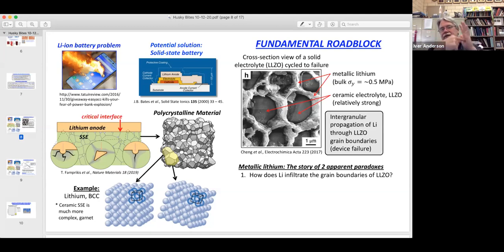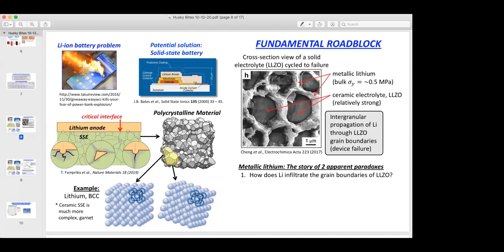Eric, is it true this oxide was put as a candidate solid state electrolyte to prevent, in the old days with the liquid electrolytes, daggers of lithium dendrites growing through? Yes, that's exactly right — this is just the next evolutionary step in that exact same problem. Some people still refer to these as metallic dendrites. And the original thinking was: we can mechanically suppress them by putting the proverbial brick wall in their way — a ceramic electrolyte — and the lithium is soft as butter, so it'll just stop any dendrites dead in their tracks.